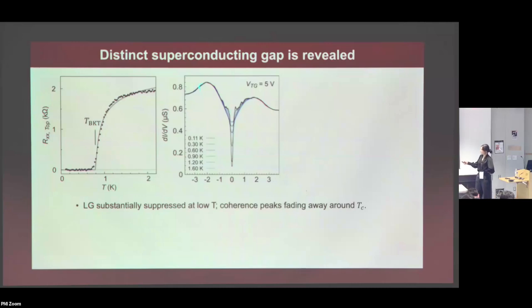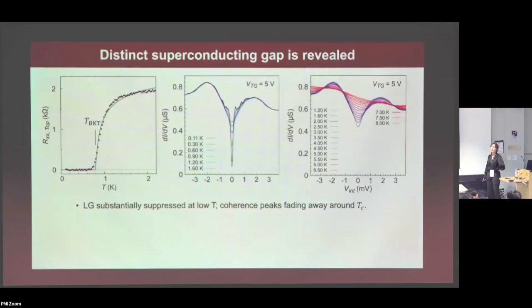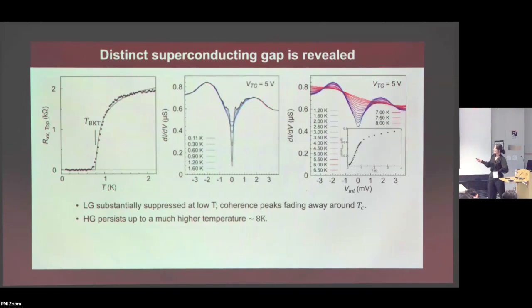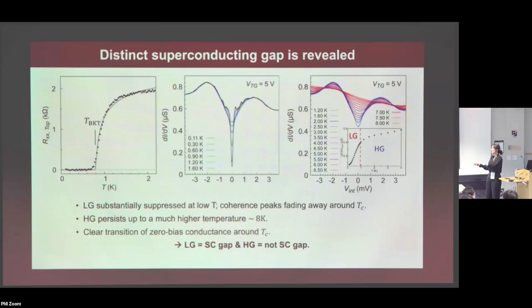So that's one observation. Now we want to know what these other shoulders are. So we can keep increasing the temperature and see that actually up to 7 or 8 Kelvin it's persistent, but then it's finally gone at such high temperatures. Another thing that we can do is to track the zero bias density of states as a function of temperature, and you can plot it here. And you can see that there's a clear transition around exactly TC where the low energy gap feature transitions into the high energy gap feature. So from this, you can already see that it looks like the low energy gap is the superconducting gap, and this high energy gap with these shoulders might be just something else.